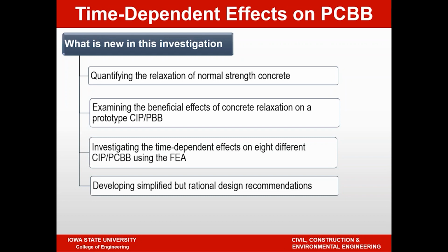and in the past it was difficult to perform a relaxation test. It's easier to perform a concrete creep test. Creep tests have been done for over 100 years, and it's fairly straightforward to perform one. Technology today exists for us to perform the relaxation test directly, so we wanted to do that rather than doing a creep test and reversing the curve.